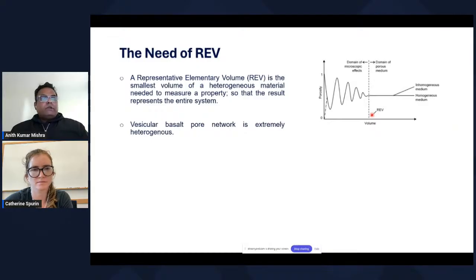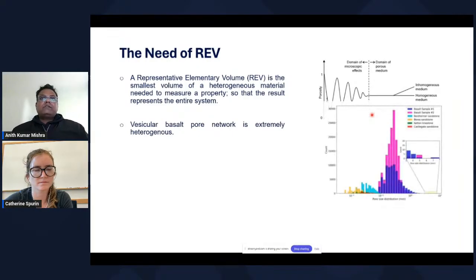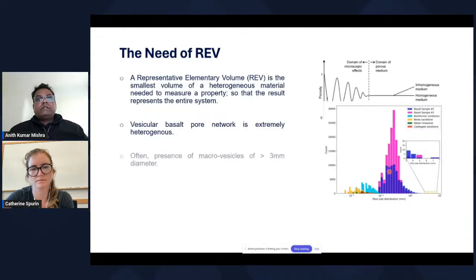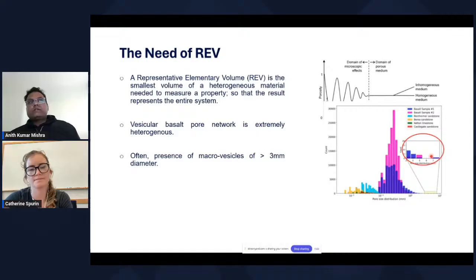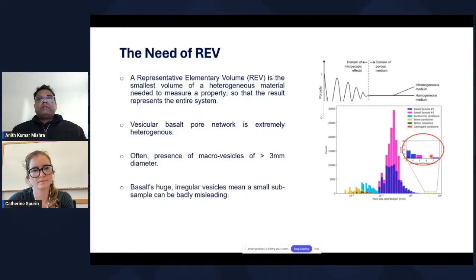Now, the vesicular basalt pore network is extremely heterogeneous, and how heterogeneous it is? This is a plot which can tell you how heterogeneous the pore size distribution within the vesicular basalt is. The left-hand side of the plot contains the most studied pore networks: Bentheimer, Berea sandstone, Ketton limestone, and Castlegate sandstone. Here in pink and blue you see the pore network distribution from the samples that we collected. Sometimes we see the presence of macro vesicles, more than 3 millimeters in diameter. So it's highly heterogeneous, with all the different kinds of pores available in these rocks. That is why it is important to establish the REV, because taking a small subsample of a basalt and using it for field scale storage estimation can lead you to very wrong results.